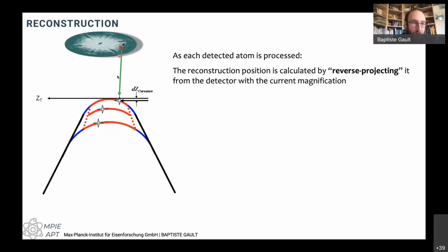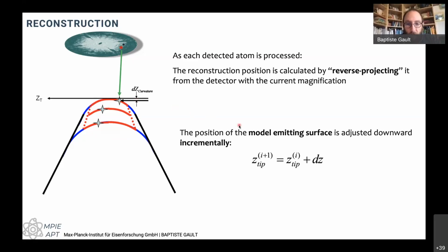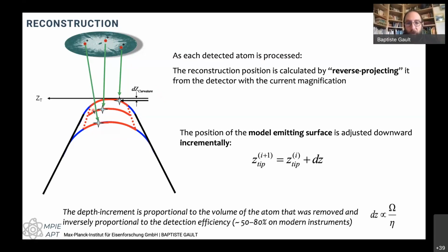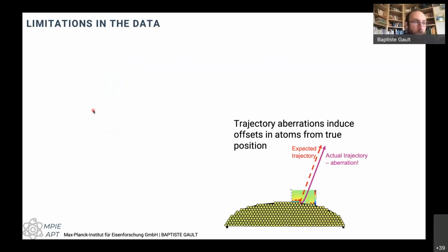So we reverse project this position onto the emitting surface, and then we just shift this emitting surface down by just a tiny amount corresponding to the size of the atom that we've detected. So a bigger atom will tend to be causing the surface to go down a bit further. Again, it's an assumption. It's a model, like most of what we do, but it works okay so far. And then we take the second atom and we position it back on this new virtual emitting surface, and then the third atom, and we do this sequentially. And every time we process one atom, we move the surface down, and process one atom, move the surface down. And so that's the way we build this 3-dimension. So it's not perfect, as I said, it's a model. We have to make assumptions, but it's not so bad.